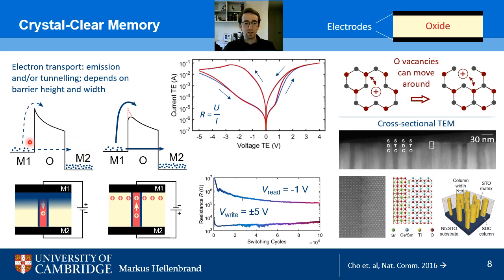So again then, electrons or electronic conduction just happens above the conduction band. So we can disregard anything that happens below these edges here and just focus on what's happening above it. So electrons in one of the metals face this barrier, and depending on the height and the thickness of the barrier, more or fewer electrons can get from one side to the other. So now by controlling the accumulation or depletion of oxygen vacancies on one side of this barrier, we can modulate its height. So if we accumulate positively charged oxygen vacancies on one side of the barrier, the height of this very same barrier will be lower than in the case of depletion of oxygen vacancies.